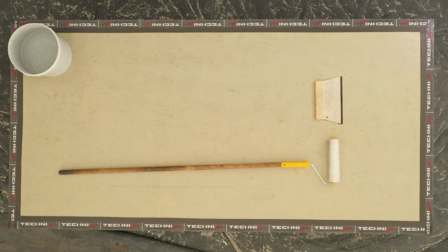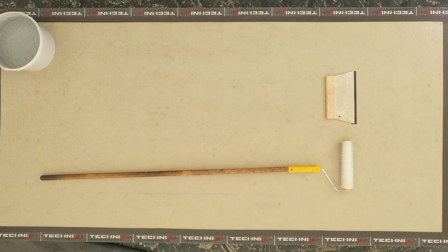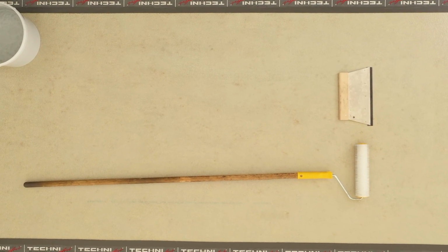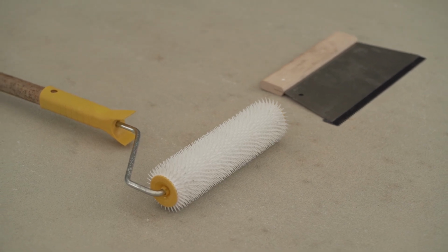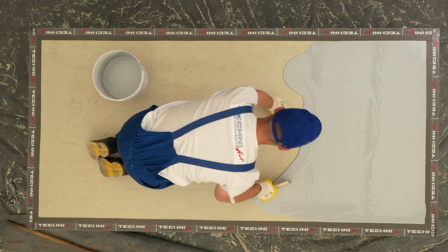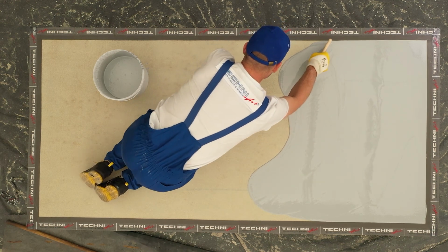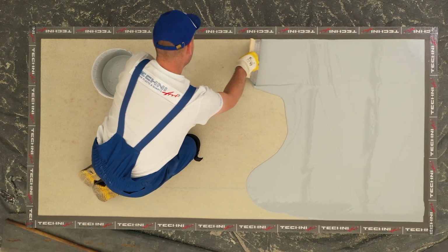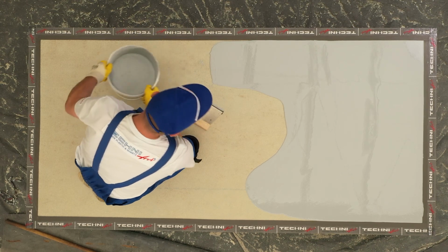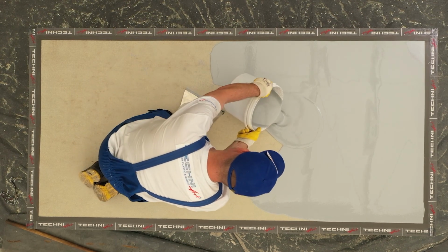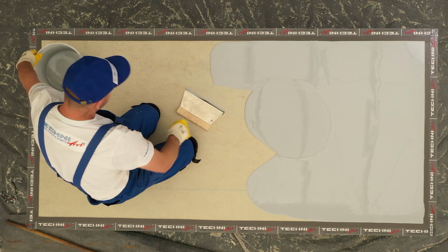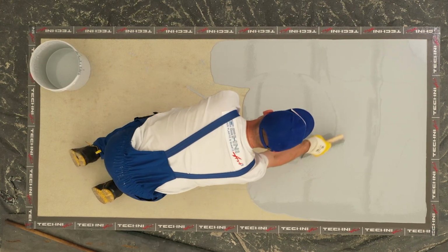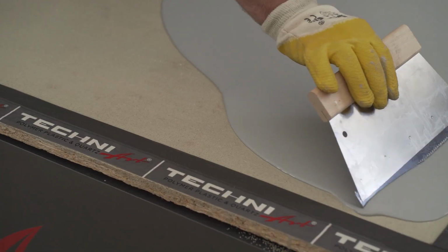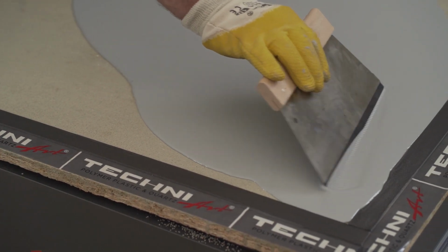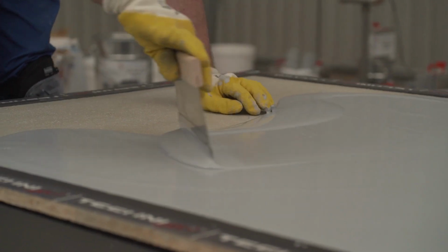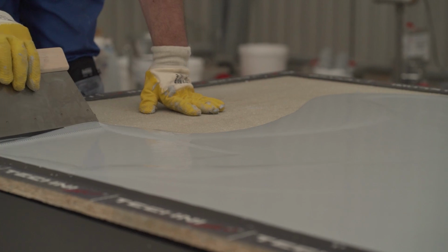To make the floor, presented in this video, using the poured method, it will be necessary to use a squeegee with a toothed insert, and a spiked roller, to vent the resin. After spilling the right amount of material on the planned working field, spread it evenly, using a toothed squeegee. The thickness of the floor will depend on the thickness of the teeth in the insert and, very importantly, on the angle of the squeegee. For this reason, it is very important to ensure that the toothed squeegee is steadily inclined throughout the resin spreading process.